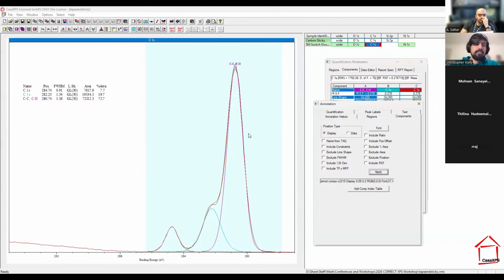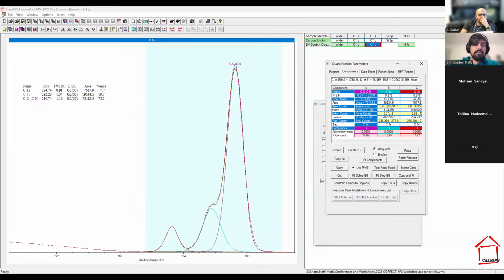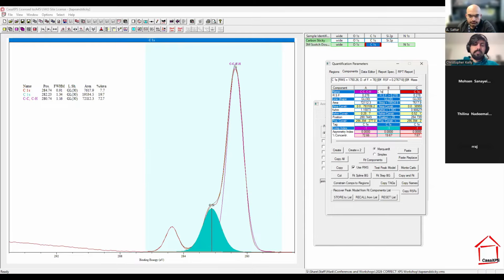For something like this, where it's fairly well defined, you could probably get away with letting the full width half maxes be unconstrained. A lot of the times, though, for something like this peak, obviously we're going to fit that to be exactly that peak width. For these 2 peaks, we may want to constrain them to have the same full width half max. So this was likely our carbon singly bound to oxygen peak.